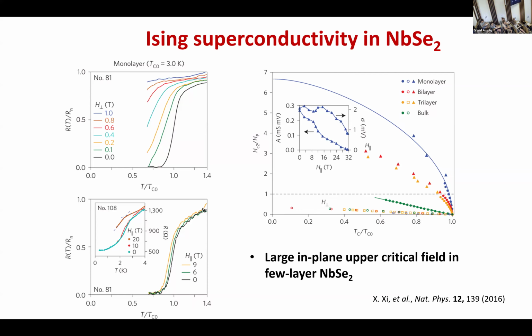Yes. And I think when people put the real numbers in there, about the spin-orbit coupling strength, you could also have a limited value. And the Rashba, I would say for niobium, and some other systems, people really go to very high field because Ising superconductivity predicts some kind of upturn, but it's not really observed in all these systems. So people argue that this Rashba effect brings your upturn down.